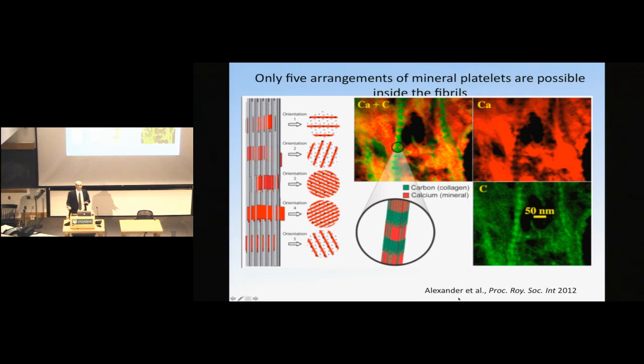We know from ashing experiments, where you take bone and burn away all of the organic components so you have only the mineral components left, what the mass fraction of mineral should be. Then using a geometric analysis, we can figure out what the volume fraction should approximately be. And so we know that bone should be about 40 to 50% by volume mineral. So we're missing some here.